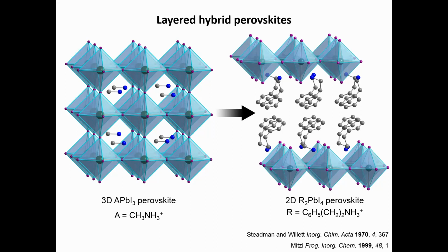They're not that stable. It depends on the composition. For example, this 3D perovskite has created a lot of excitement in the field because it has some really nice photovoltaic properties. But it also has methyl ammonium, and methyl ammonium iodide, if you heat this at 60 degrees, you lose methylamine. So they're not heat stable. Some of these materials are not light stable. This material is not moisture stable.